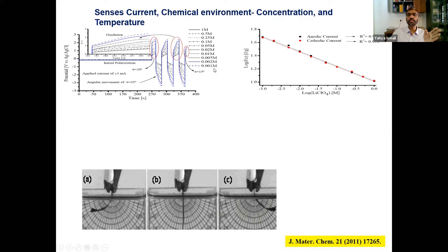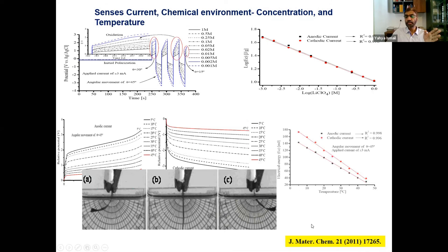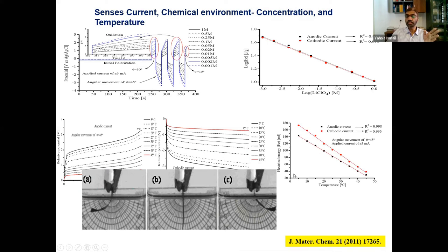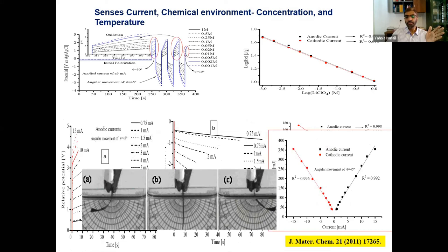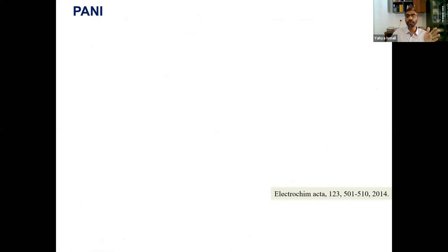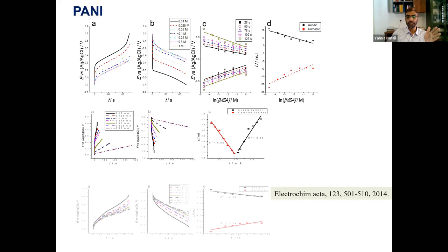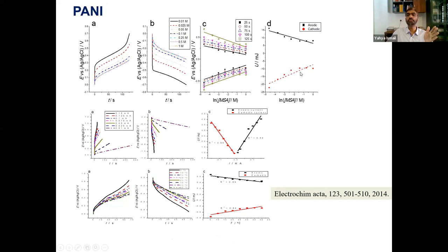This material is able to sense the surrounding chemical condition. We tried different temperatures, and it was able to sense the temperature without any more connectivity, with the same connecting wires. Then we tried different materials, not only polypyrrole, but also polyaniline microfiber and silk nanofibrous mat. This material is able to sense the electrical working condition, chemical working condition, and temperature of the surrounding.